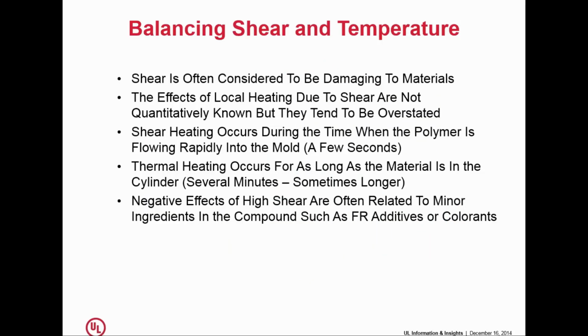Now, the other problem we have in this industry is that shear is very often considered to be damaging to materials. It is true that there is some heat generated when we shear a material. We know that to be the case. We don't know how much, and the answer is going to be different for each material. We are still working out the details of how much temperature truly is contributed by higher shear rates. What I have seen, though, is that whatever the contribution is, it tends to be overstated. People tend to think they're doing a lot more damage than they really are.